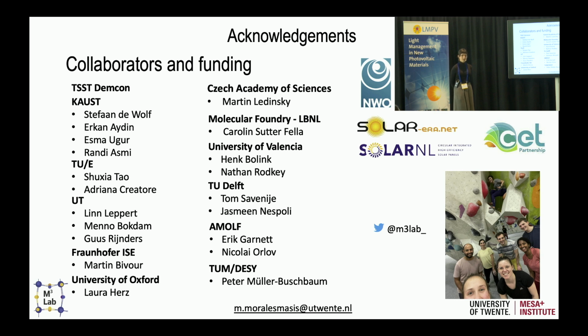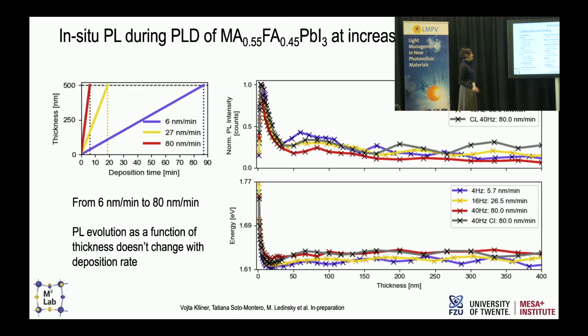I'm really curious. Yeah, good point, I forgot to mention that. When we increase the deposition rate, we basically change the frequency of the laser. For epitaxy we use 1 hertz, for the cells it's 4 hertz, and here we went up to 40 hertz. And there are lasers that can go to 100 hertz. We don't have that laser, but it is possible. To increase the deposition rate is just the laser frequency, because it's basically the amount of material you are ejecting from the target every time. If it's 1 hertz, you deposit once, then you wait, and then you go for the next one. And if it's very fast, you're depositing very quickly.